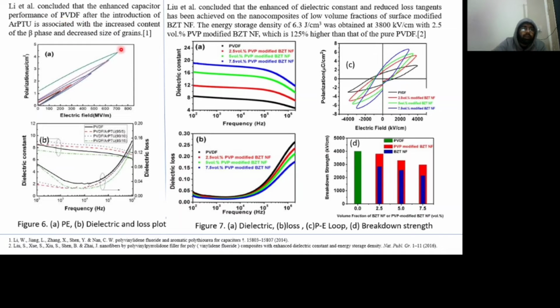Li et al. show the nanocomposite of PVDF with a filler, aromatic polythiourea. In this, with the help of this filler, the polarization is increased and the dielectric constant also increased. Liu et al. used the BZT nanofiber as filler in the PVDF matrix, and he got a very good dielectric constant, and dielectric loss also decreased. They have got very good polarization, enhanced with the loaded filler.